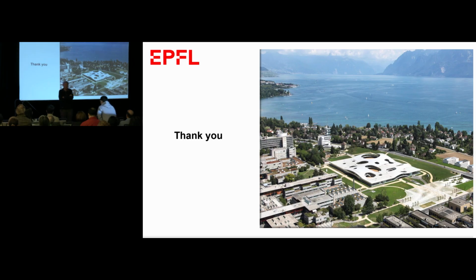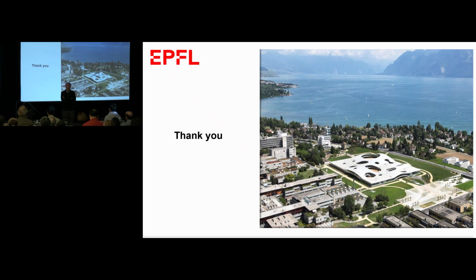Yes, in many ways we can learn, but perovskite solar cells are more challenging than dye-sensitized. The dye-sensitized, you can't kill them. If the dye is on the surface and you have something that regenerates it, they will work. And even if that dries out, you put a little bit of ionic liquid back and they will run again. The perovskites are much more complex. I mentioned the compositional complexity, structural complexity. However, it's amazing how stable they are now.